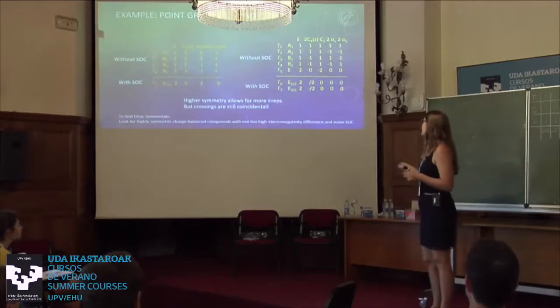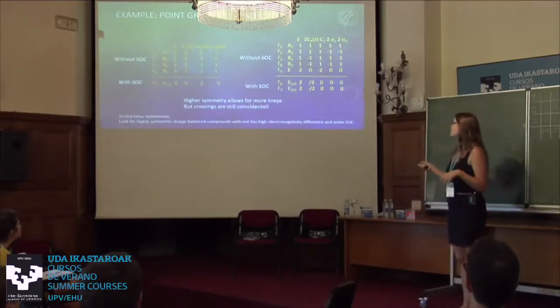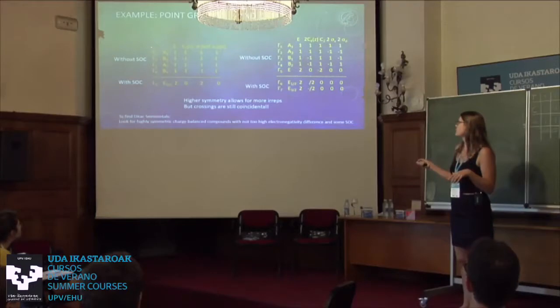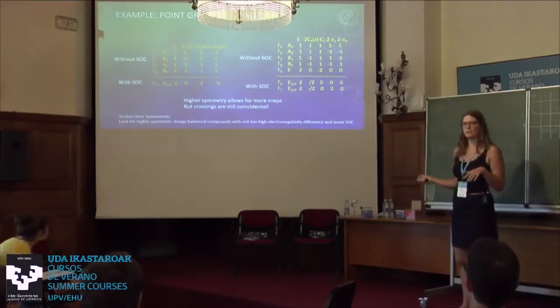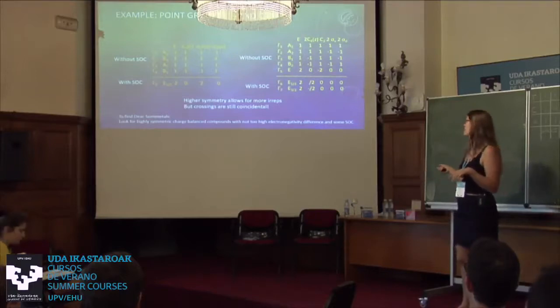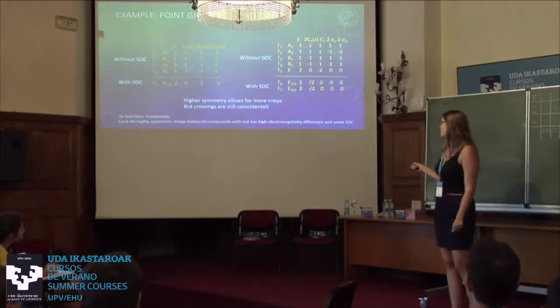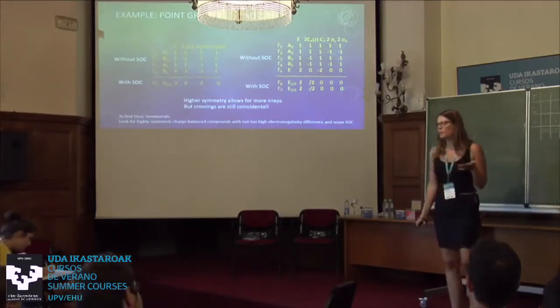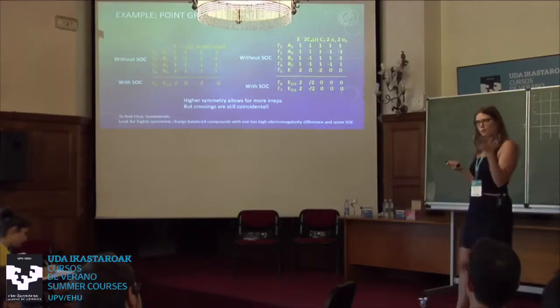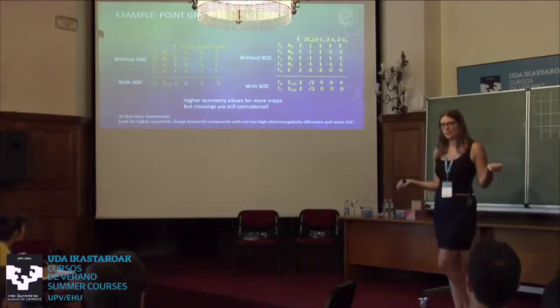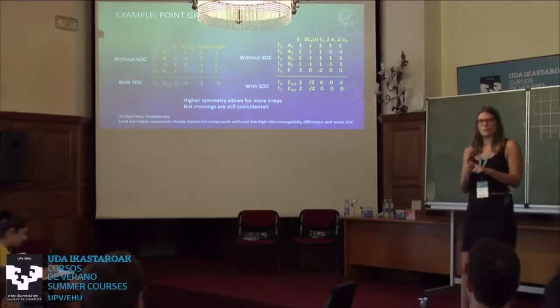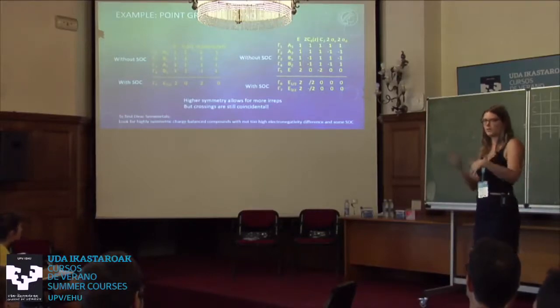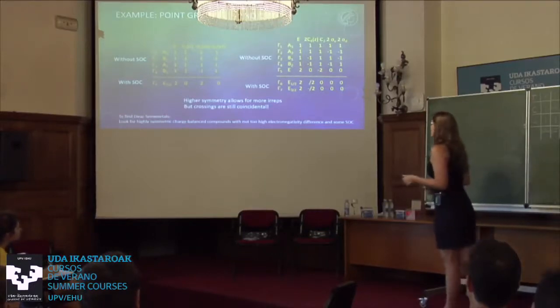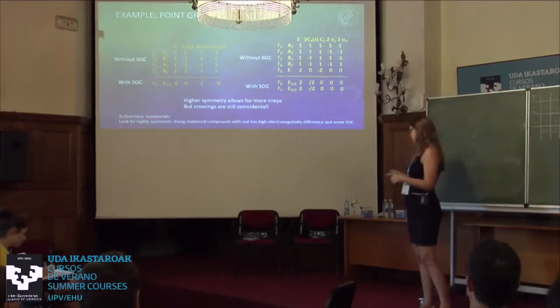Here's again, I think this is easy for you, but here's again how you see how spin-orbit coupling reduces the number of IRREPs. Why we have, for example, in the C2v point group four possible ones without it, they're reduced to one with spin-orbit coupling, but with the fourfold axis, we still have two. It's important to point out, because this also depends on orbital character, if we have a fourfold symmetry axis, it's possible to have a 3D Dirac semimetal with two different IRREPs, but it's not a given. Okay, so this is just a guideline. We want to have high symmetry materials.